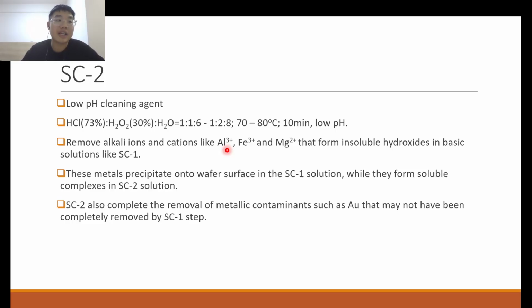And so that's not good, because then it precipitates out your metal hydroxide that can then rest on the surface, and then it becomes a particulate contamination. So that's not desirable. So what we do is that we use SC2 to dissolve these insoluble hydroxides through an acid-base reaction, because your SC2 is an acidic solution, and then it's able to wash away the dissolved ions. And in addition, SC2 also can further complete the removal of any metallic contaminants such as gold, through an oxidation reaction. They may not have been completely removed by the previous SC1 step.